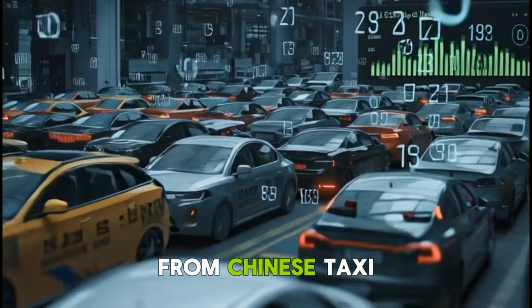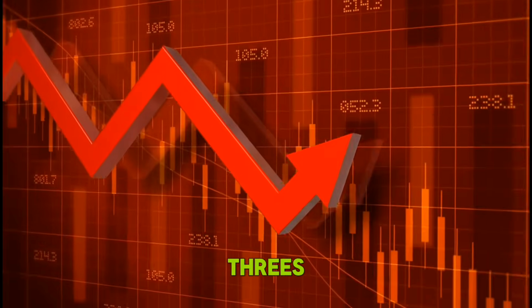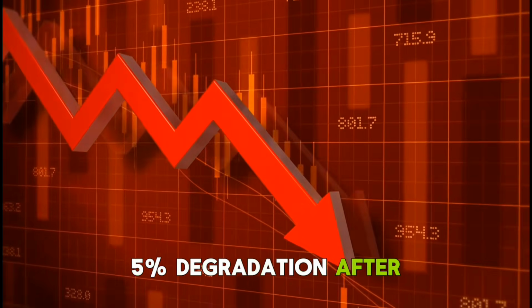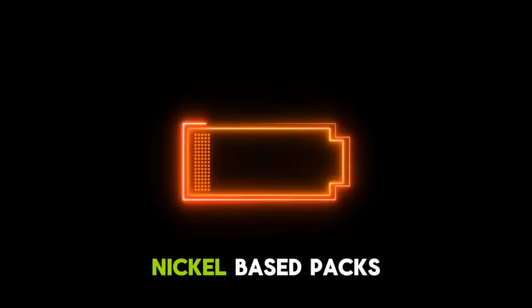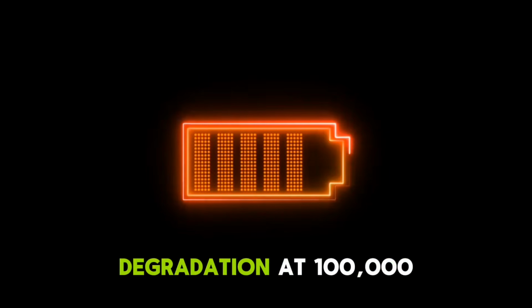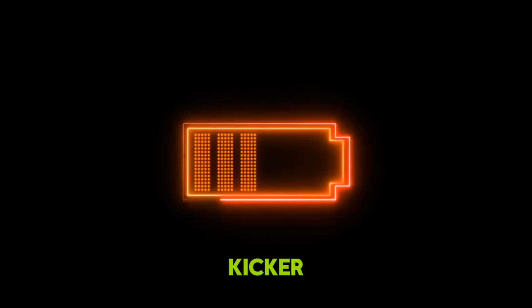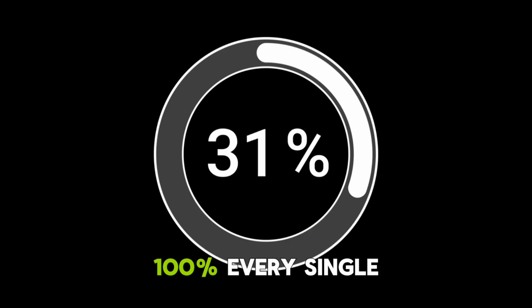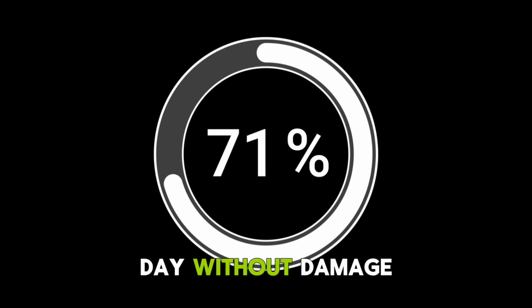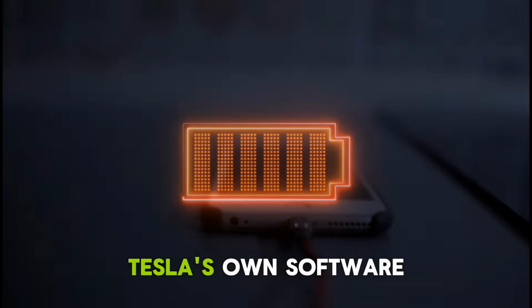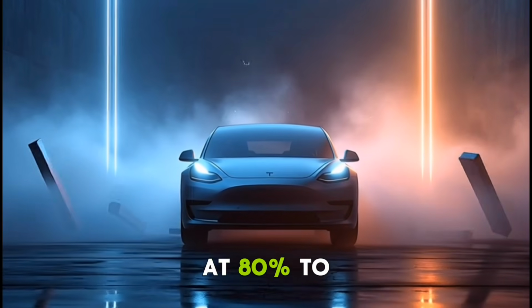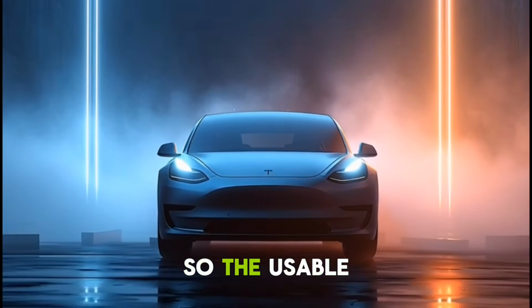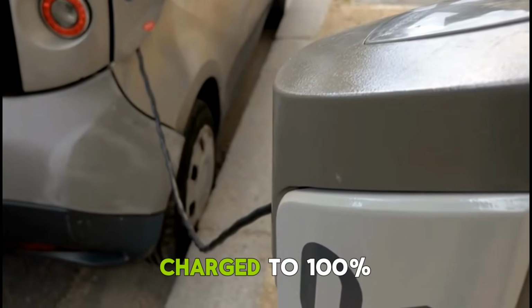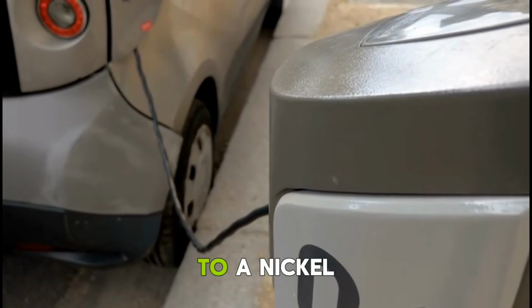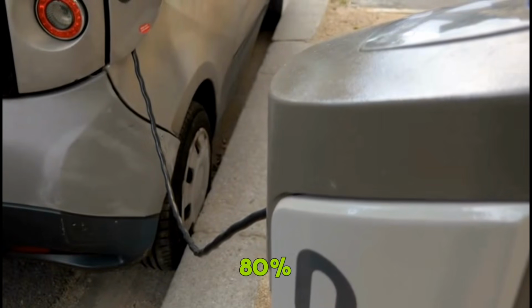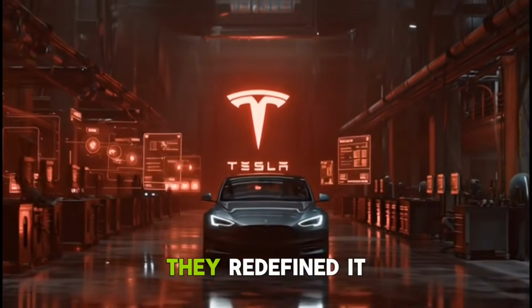Real-world data from Chinese taxi fleets running LFP Model 3s shows less than 5% degradation after 130,000 miles. Nickel-based packs? They're hitting 10% degradation at 100,000 miles. And here's the kicker. LFP batteries can be charged to 100% every single day without damage. Nickel-based packs? Tesla's own software recommends you stop at 80% to preserve longevity. So the usable range of an LFP pack charged to 100% is often identical to a nickel pack charged to 80%. Tesla didn't abandon performance, they redefined it.